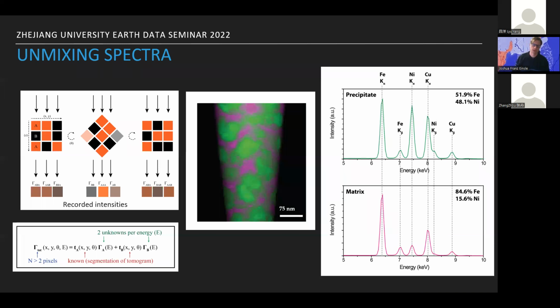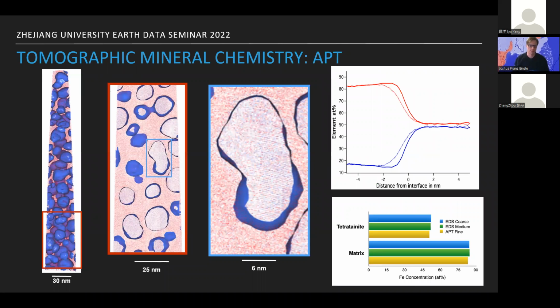At first, this seemed a little high, but then we turned our attention to our atom probe data. Here we're now looking at particles from the fine cloudy zone, so these are tetrataenites that are 50 to 30 nanometers in size. When we looked at these grains and at this analysis using proximity data, we can see that our results for both the matrix and the tetrataenite particles were within 1% error of what was predicted from atom probe.